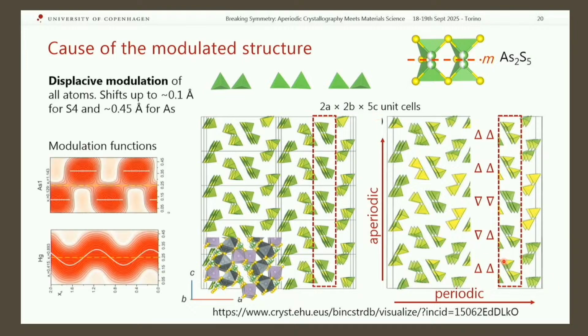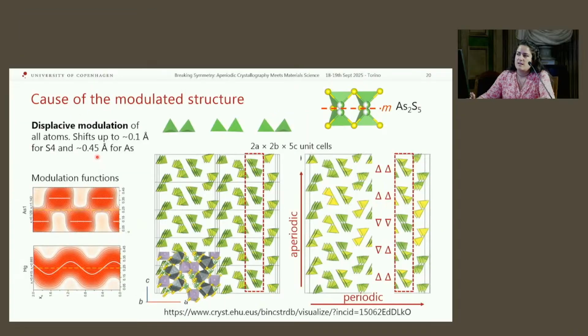So this is, again, the origin of the modulation: the frustration of the arsenic. So it's a displacive modulation. The arsenic can be either up or down, and it's occupying these 2 positions with a discontinuous modulation function. And in doing so, the arsenic is actually dragging along all the other atoms. So they also respond with a displacive modulation, even though to a lesser extent, but it's still half an angstrom or 0.3, 0.4. So all the atoms are modulated, and they are described with their modulation function.